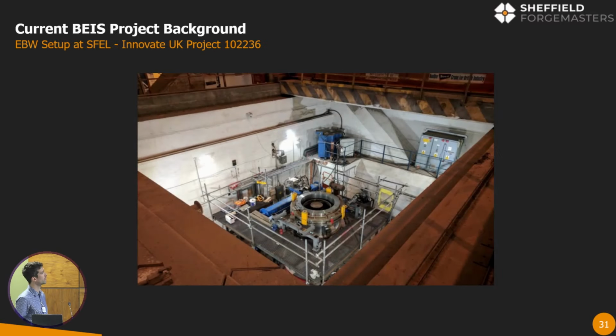And we managed to achieve this on site at Forge Masters by bringing the electron beam welding equipment down from TWI up in Middlesbrough, and utilising a local vacuum jacket to facilitate the weld in Forge Masters. So we have an X-ray pit on site where we did that welding. That's what the photograph is showing there.